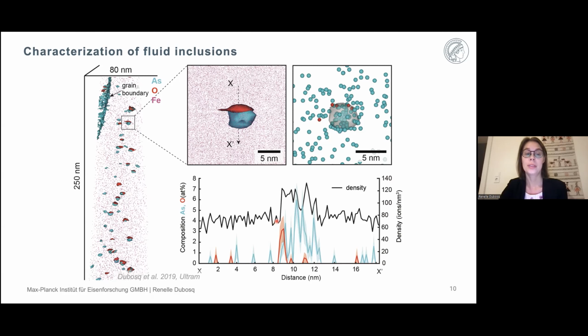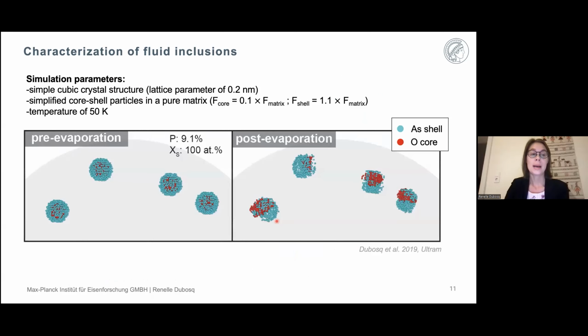So to confirm that these features that we've documented are truly fluid inclusions, our collaborators at the Groupe de Physique des Matériaux in Rouen conducted some field evaporation simulations. In this case, they used a meshless finite element method to simulate field evaporation of a specimen containing fluid inclusions. The specimen geometry was simplified to a hemisphere on a cylinder with a simple cubic crystal structure. The lattice parameter used for these simulations was 0.2 nanometers.